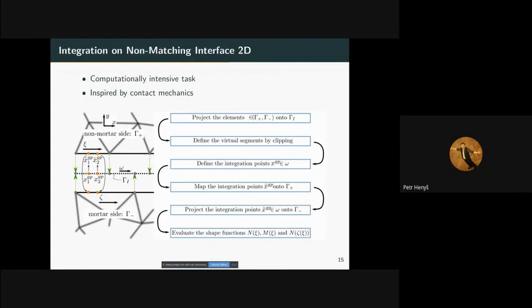So you need to find some mapping scheme, which we tried in our cases, that we define firstly as something like an intermediate surface, an integration surface, and then we try to remap those Gaussian points to both sides. If we did it that way, we get really precise results. Actually, we get exact results in terms of the order of the integration, in terms of the order of the quantities integrated, and also the interpolators usage, right?